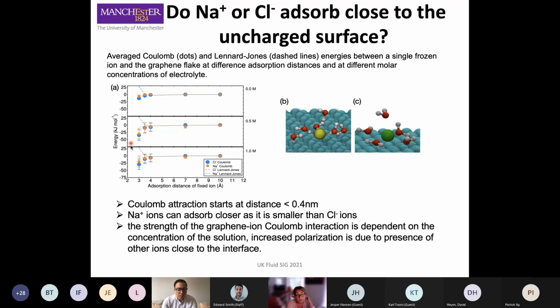And then what you can do is we just calculate the energy of these ions as it was approached. So we basically have a fixed ion that approaches the surface at different distances, and then we have an electrolyte nearby, and then we calculate how much is the energy between the ion and the carbon, so the surface of the graphene, as the ion approaches. So, and we separate the Coulomb term from the Lennard-Jones term. And we look at this at different concentration again. So when the ion is far away, of course, it doesn't feel the graphene at all. And then it starts to be actually attracted from the Coulomb, from the electrostatic interaction when it's roughly at 3 angstrom.